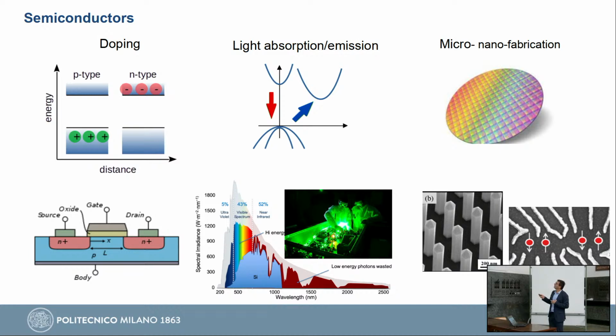The other characteristic of a semiconductor is that it can emit or absorb light very efficiently, especially if it is a direct gap. And we have seen that we can actually tune or choose between different materials with different gaps. So one application for light absorption is, of course, a solar cell. So what you see here is a spectrum of the radiation reaching the Earth from the sun. And you see the part of this radiation, of this energy, which is collected by silicon, for example. So a different semiconductor will cover this area differently and give you a solar cell of different efficiency. So if you want to maximize your efficiency, you also have to choose the right semiconductor. Silicon is the right one, also for economical reason, because it's one of the most abundant elements on Earth, and it has a large chemical infrastructure to purify it.